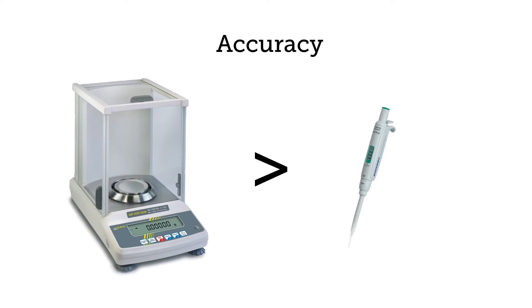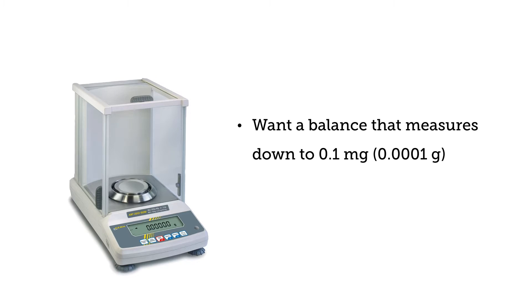To prepare what we call a quantitative sample you first need an analytical or semi-analytical balance. These are balances that measure weights in the submilligram range. An ideal balance for this would be one that measures as low as 0.1 milligrams because often times the nanoparticle sample volume can be quite low in the 10 to 100 microliter range.